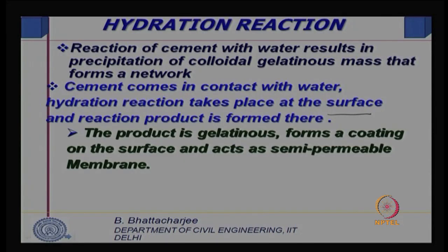Now, next what will happen? The product, of course, is colloidal and gelatinous, and it forms a coating on the surface of the cement itself. This coating acts like a semi permeable membrane.